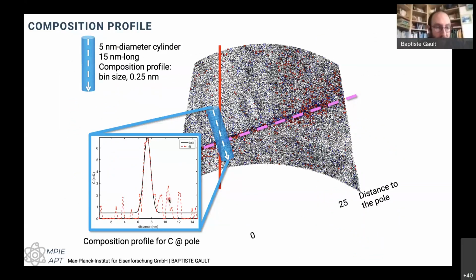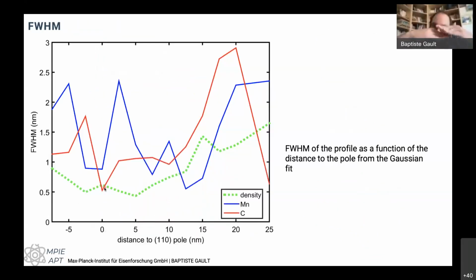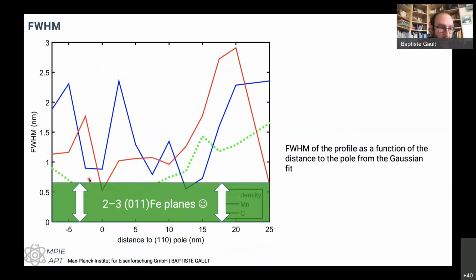And what I get is that right on the pole where these atomic planes are well reconstructed, I can see that the width of the profile will be 0.5 nanometer, so just 2-3 atomic planes maximum. And same thing for the manganese, it can go down to about 0.5. So the segregation will only take place over 2 to 3 atomic planes of the iron matrix.